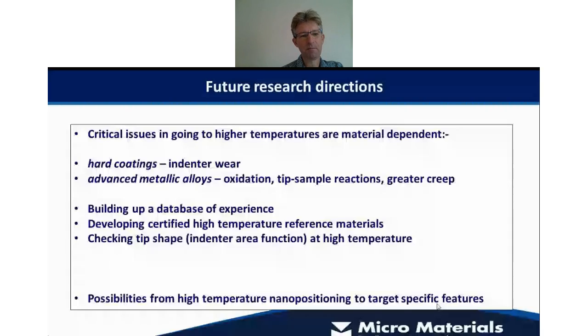And over the years, we've built up a database of experience in how we design our type of tests. And going forward, I think there's going to be increasing use of certified high temperature reference materials with known elastic properties at high temperatures. We can use these particularly in our high temperature campaigns, and we can test them to provide an indirect verification of the tip shape area function at high temperature, to check we have no wear, and this then gives an extra data assurance of the high temperature results.